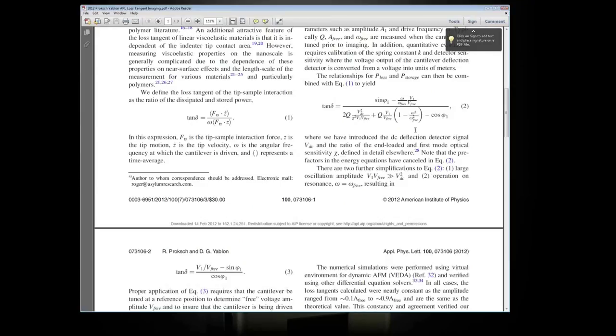So in this case, this expression here involves this omega squared over omega free, and that allows you to plug in any omega you would want. So theoretically, if you have a nice smooth transfer function to your cantilever, you can go anywhere. I should note, though, that there are some assumptions in the optical lever sensitivity that you have to account for in this, and especially that first expression in the numerator here does not cancel out. So you don't get this beautiful independence from the optical lever calibration.